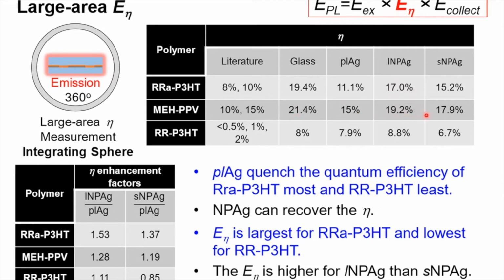This was the same for the MEHPPV as well. Interestingly, for the regioregular P3HT, we didn't see a strong effect or change in the quantum efficiency on those two porous metasurfaces. So in general, we found that the planar silver quenched the quantum efficiency of the regiorandom P3HT the most and the regioregular P3HT the least.